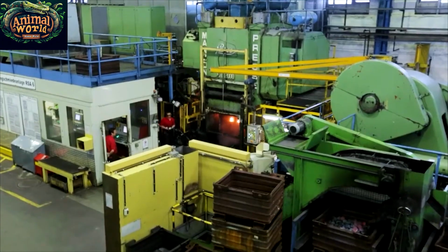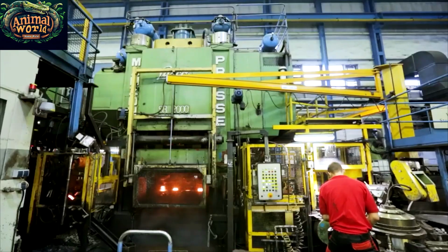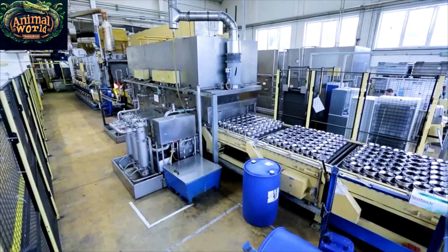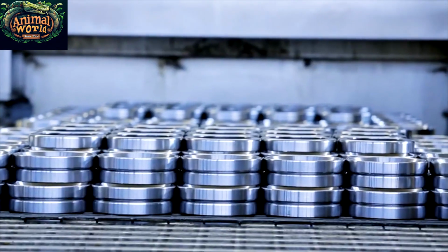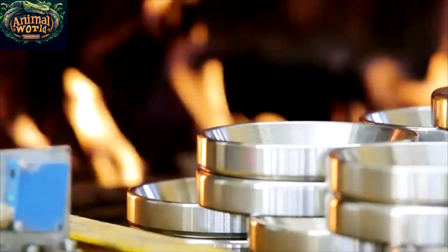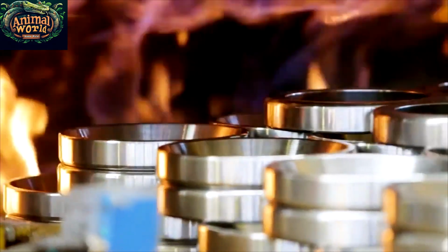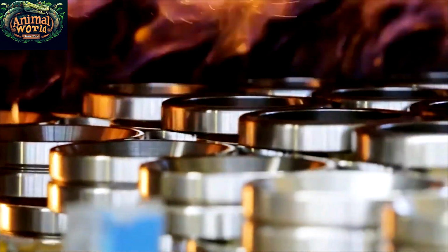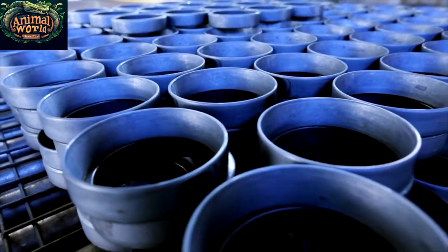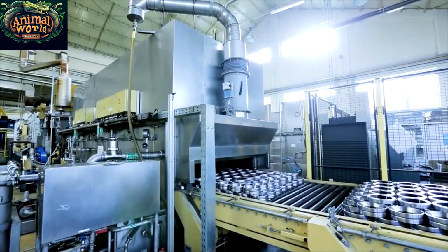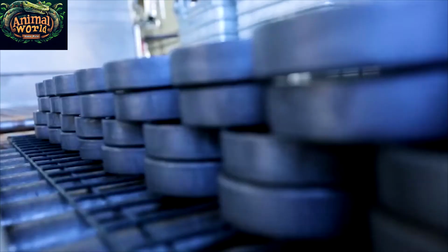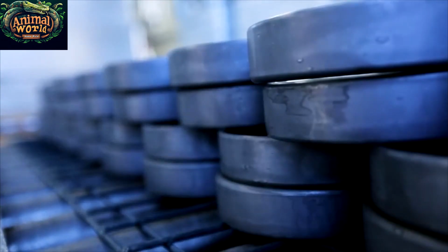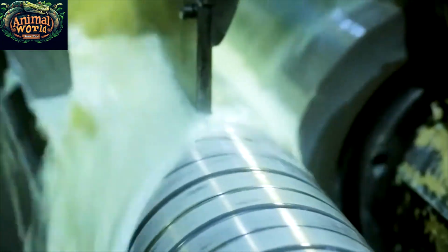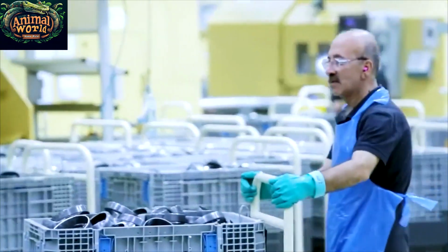The rough-cut races are put into a heat-treating furnace at about 1,550 degrees Fahrenheit, 843 degrees Celsius, for up to several hours, depending on the size of the parts. Then dipped into an oil bath to cool them and make them very hard. This hardening also makes them brittle, so the next step is to temper them. This is done by heating them in a second oven to about 300 degrees Fahrenheit, 148.8 degrees Celsius, and then letting them cool in air. This whole heat treatment process makes parts which are both hard and tough.